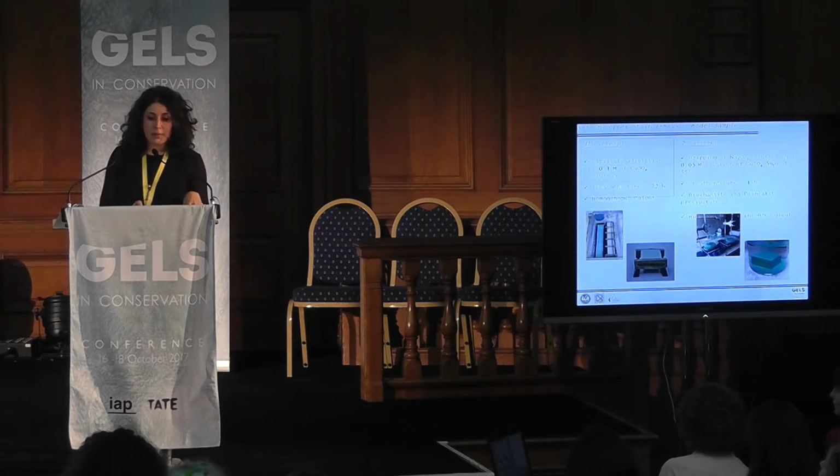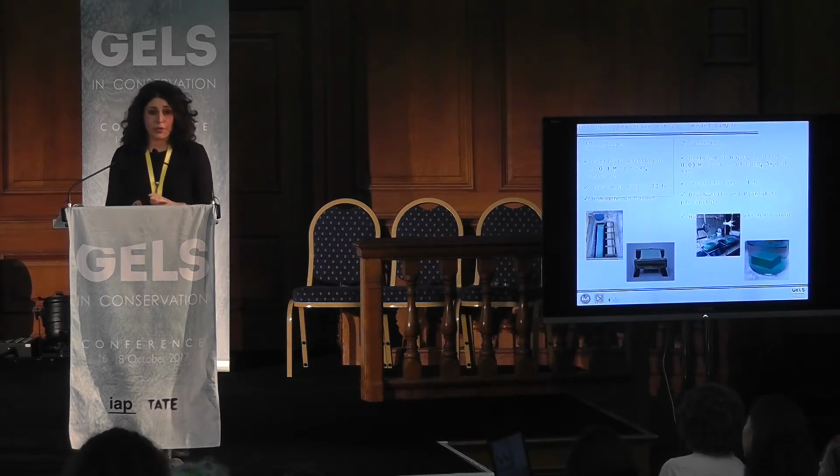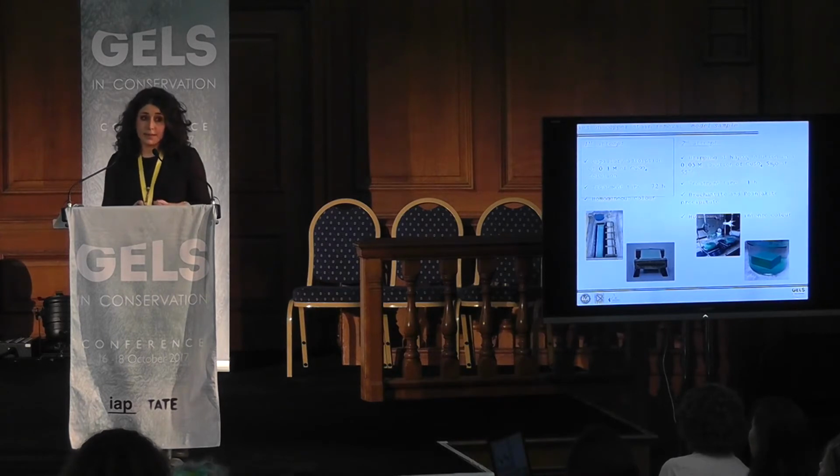In the first attempt, marble specimens were stained with a copper sulfate solution by capillarity for 72 hours. In the second attempt, marble specimens were stained with a solution of copper sulfate and sodium carbonate, released by dripping for 1 hour, by immersion in this case.